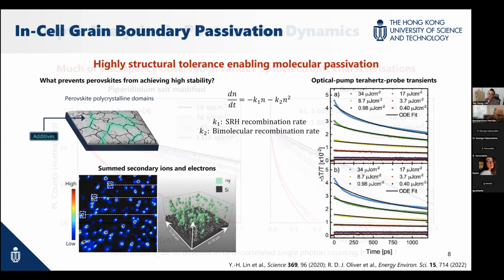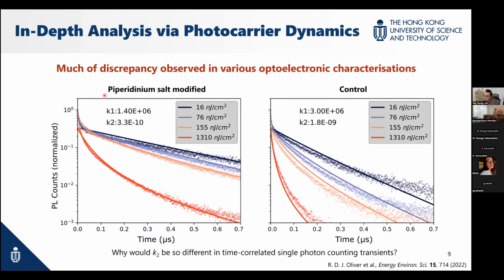So we have the K1, we have the K2. K1 is the constant for the monomolecular recombinations. K2 is for bimolecular recombinations. But something odd here is when we compare the modified one and the control one, the K2 shows a significant difference.